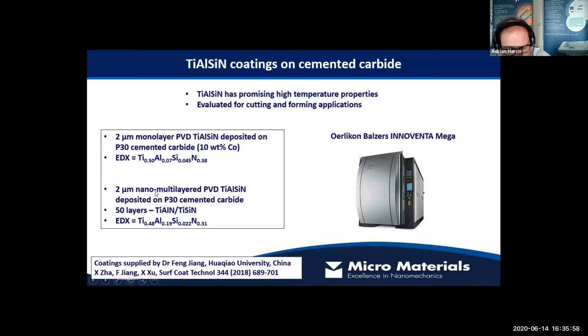The other one is also 2 microns, but it's a multi-layer coating. So it's 50 alternate layers of titanium aluminium nitride and titanium silicon nitride. Okay, so this is just a bulk layer of titanium aluminium silicon nitride. So that's the difference between the samples.